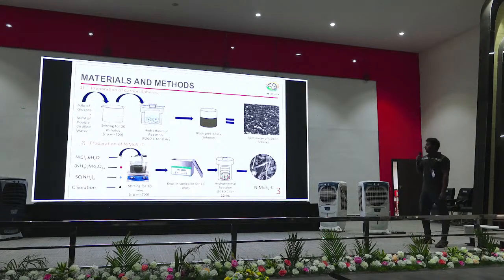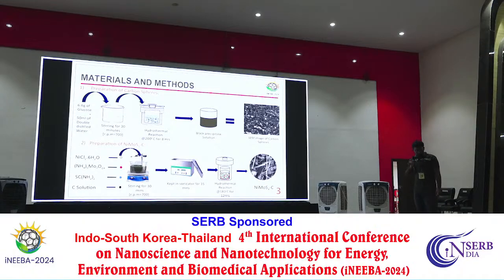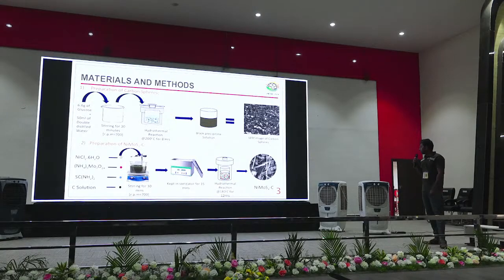It was stirred for 30 minutes, and after that, sonicated for 15 minutes. It underwent hydrothermal reaction at 180 degrees for 12 hours. After that, the prepared solution was washed with ethanol and water and dried overnight at 80 degrees Celsius. The prepared material was nickel molybdenum sulfide with carbon.